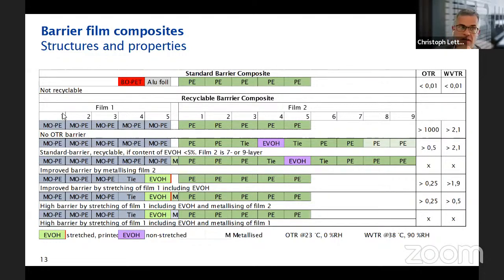And unfortunately, if we now compare this with the pouch which I just showed before, consisting of a monoaxially oriented PE film and the lamination PE film, we are far away from any kind of barrier function, which is for sure needed for lots of applications. The beauty of this one is that it is for sure recyclable. The beauty of this one is the good barrier function, unfortunately not recyclable. So what can we do?